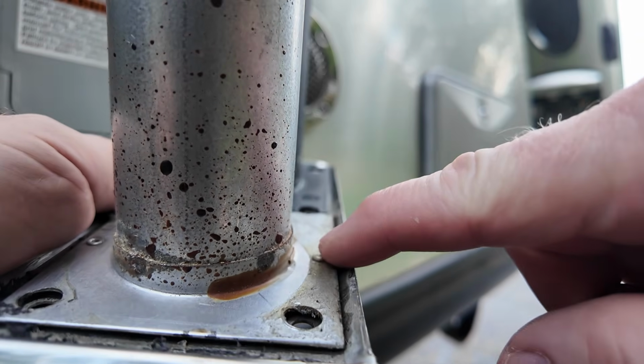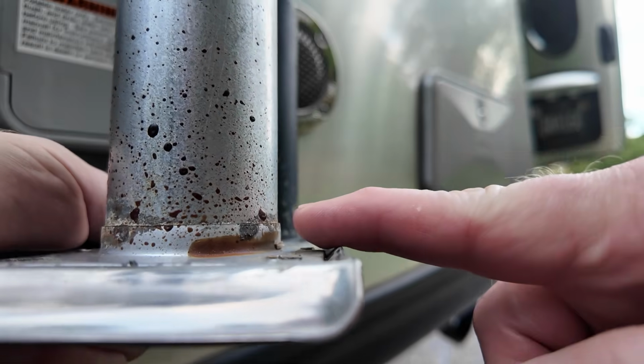Practically speaking, the edges of that stainless trim plate are relatively sharp. Not chef knife sharp, more like sandpaper, pretty harmless at first, but as the trailer vibrates, that edge cuts through the clear coat until it comes in contact with the bare aluminum underneath. Add a little moisture, like I did at the car wash, and physics will create a galvanic cell. Now, a galvanic cell is essentially a low voltage electrochemical battery. It forms when two dissimilar metals are electrically connected through an electrolyte, like water. The aluminum acts as the anode and corrodes to protect the stainless. In so doing, it accelerates the Filiform corrosion already underway, driving those spider webs even further beneath the clear coat.